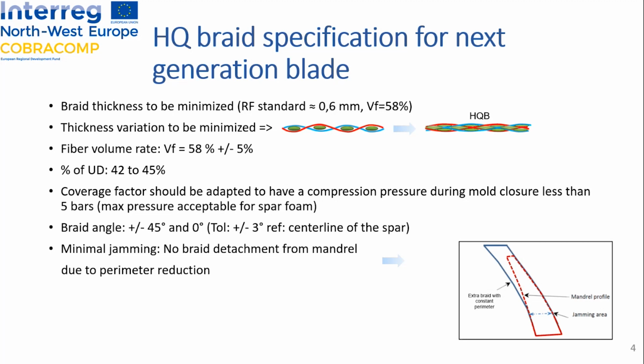But we have to minimize the difference between the two thicknesses. Thanks to the new yarn position and movement, the thickness variation of the new high quality braid will be minimized. As Stefan has already explained, here you can see some curvature of the yarn braid, and thanks to the HQ braid, this variation will be less compared to the classic braid structure. The fiber volume rate reached will be the same, 58%, and the UD ratio will be from 42 to 45%.